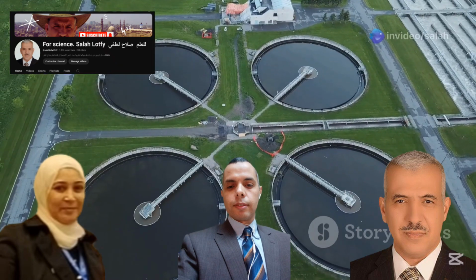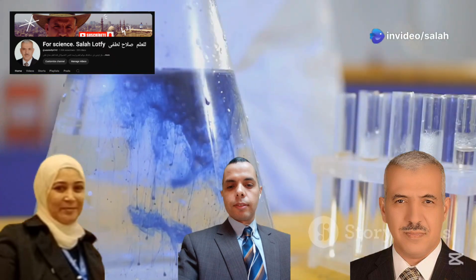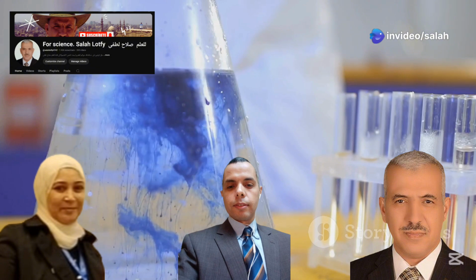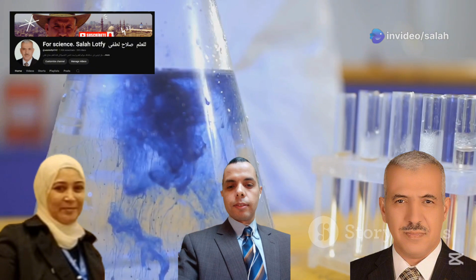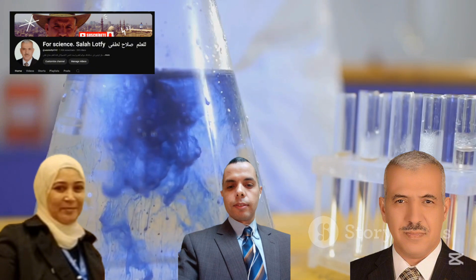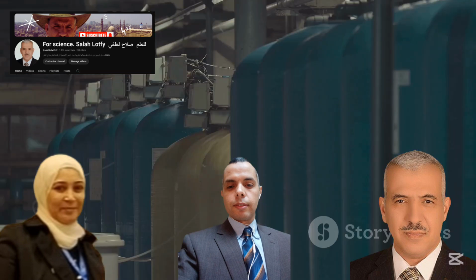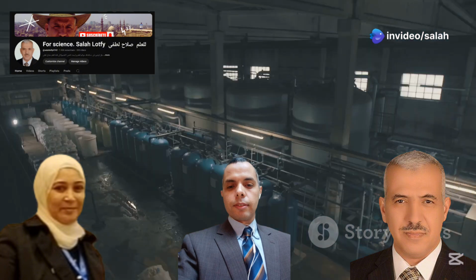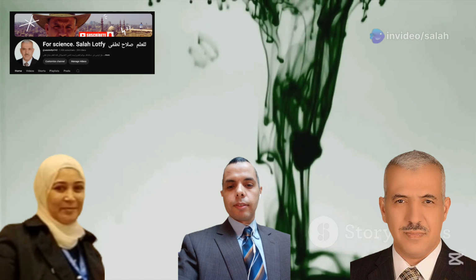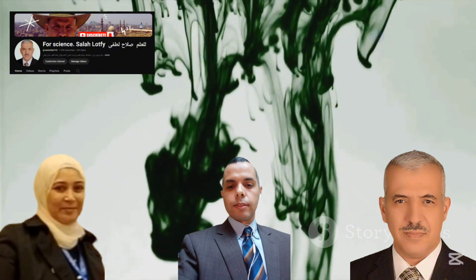But how does it work in the real world? When they tested it on industrial ink solutions, these hydrogels achieved an impressive 87.5% separation rate. That means they could recover water through a process called forward osmosis. This is huge for industries. Imagine reducing waste while reusing purified water. The hydrogels also showed excellent water retention, with only 75% of absorbed water evaporating over 50 hours.